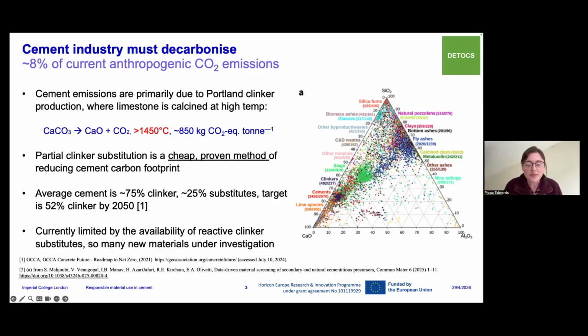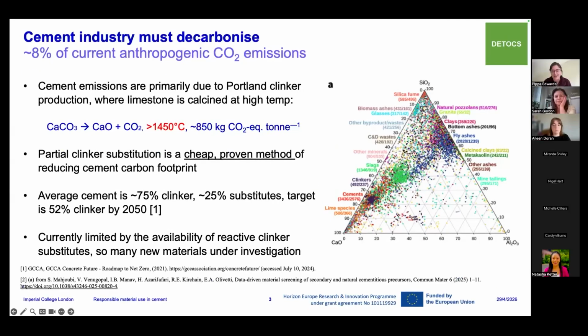One of the challenges in reducing the clinker content from today's levels is the availability and the reactivity of substitute materials, which has driven significant research into identifying potential materials. And that's demonstrated here on the chart on the right, which encompasses all the literature into researching new material compositions that we can use in cement. That includes traditional substitute materials like blast furnace slags and fly ash, to exploring areas like mine waste, biomass ashes, and even new manufactured products like calcined clays.